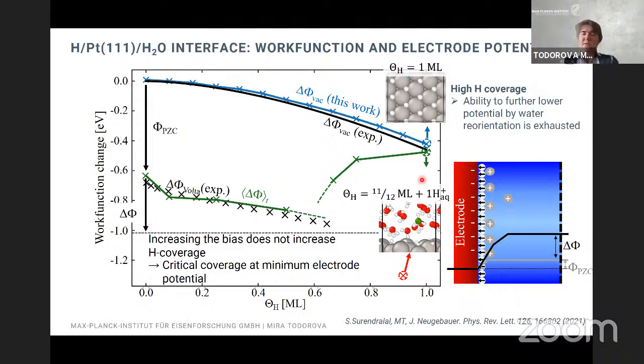Indeed, when we look at our calculations at 1 monolayer coverage, we find after about 20 picoseconds that there is a desorption process. So we form here a hydronium ion, and this leads to a tremendous drop in the electrode potential. So this kind of structure seems to be only metastable, and within our computational time, we could see this process for the 1 monolayer cases. We find also rather slow convergence of these structures that we have looked at here. And quite obviously, we do have some kind of change in the behavior within this region.